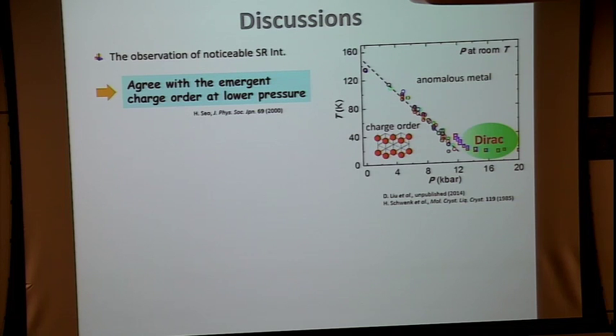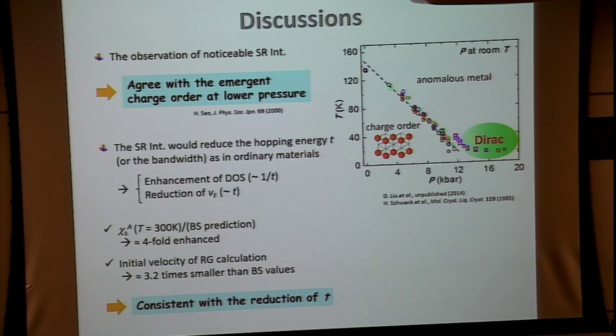So, in organic massless Dirac electrons with tilted cones, there are two important effects. One is the long-range Coulomb interaction effect and the other is the short-range Coulomb interaction effect. That is reasonable because, as I said, the charge carrier density is vanishingly small at low temperature, so the long-range Coulomb interaction is not screened. And on the other hand, the charge ordered state is neighboring. So short-range Coulomb interactions are equally important in these materials. Okay, 10 minutes over.